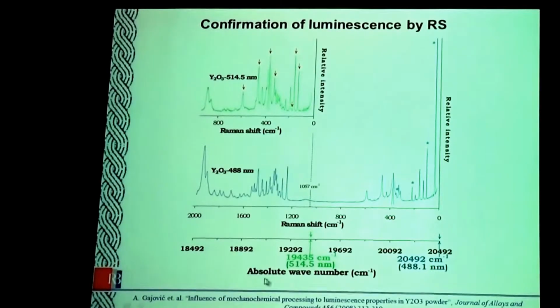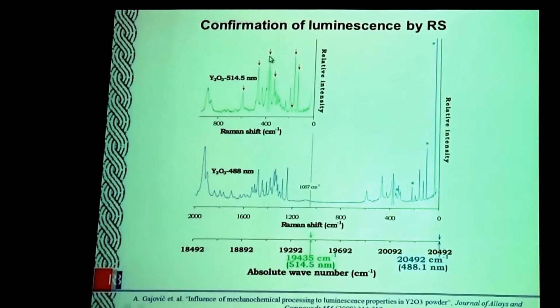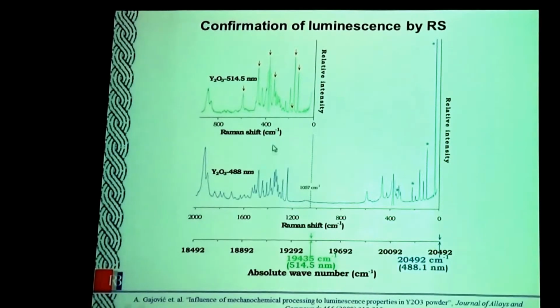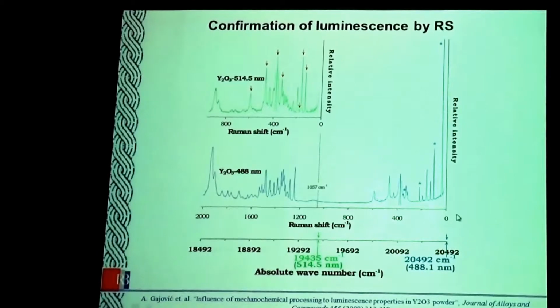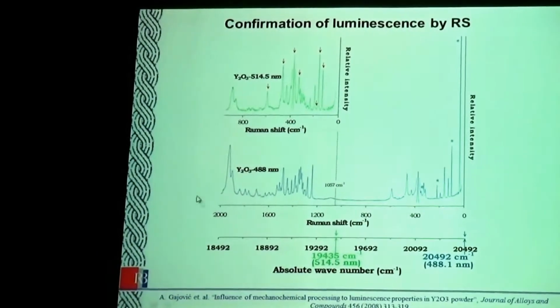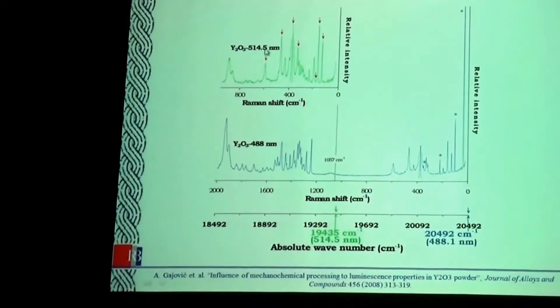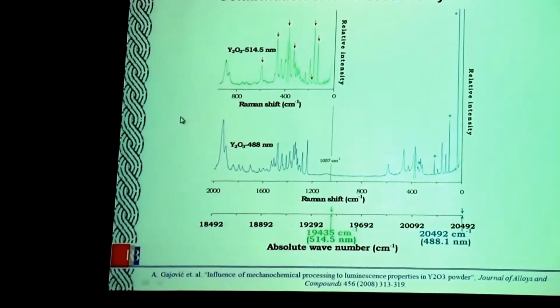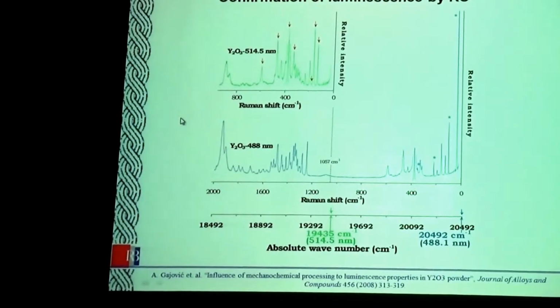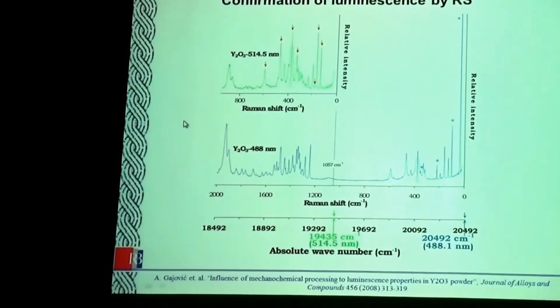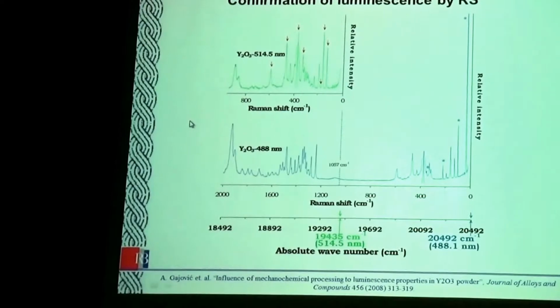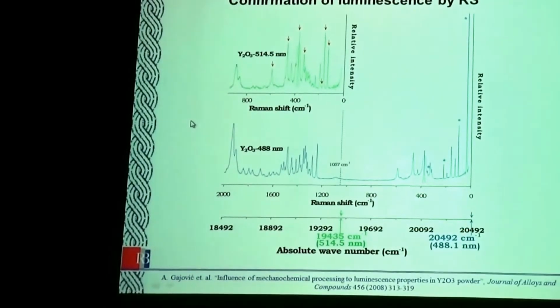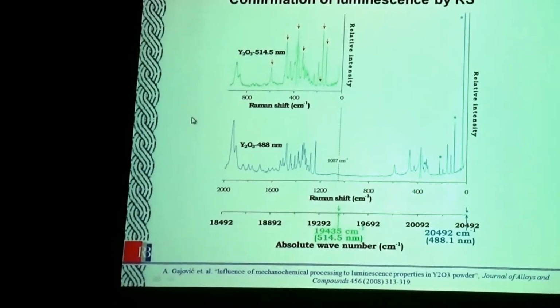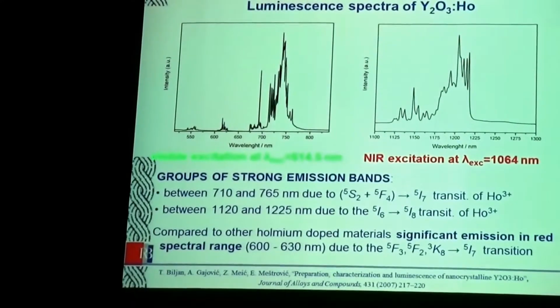So if we look at the absolute wave number, this luminescence band will always be at the same position after illumination, after scattering, while the Raman bands will be shifted. Every time we are looking only at the Raman shift, so our spectra will look different, but when we compare them, we can easily recognize the luminescence line. So in this way, if you are not sure that you really have Raman bands, you can just change your excitation wavelength, and then you will be sure. Or you can send it to colleagues who have different lines. So this is how to recognize what is going on.